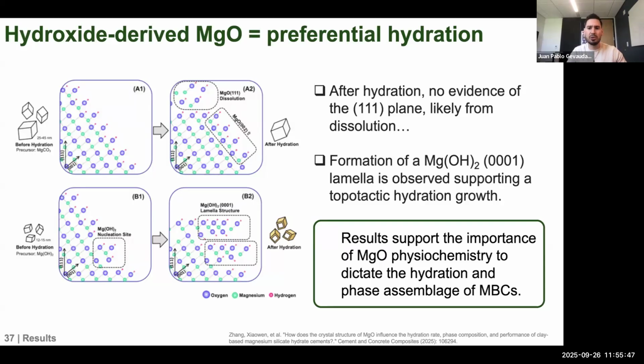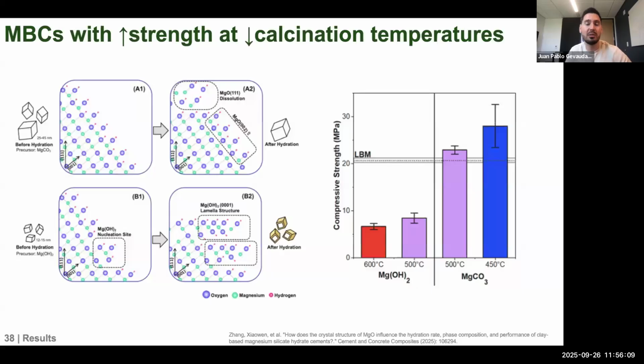And really what these results show is that there is a really critical importance on the physiochemistry of that magnesium oxide. It really matters, the physiochemical properties of magnesia, to dictate the hydration and the phase assemblage of any magnesia-based cement. And if that is not convincing you, then let's look at some of the strength results that we have.